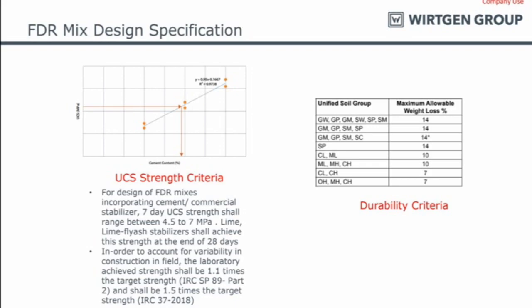As per the specification for FDR mixes incorporating cement as well as commercial stabilizer, your 7-day strength should come in between 4.5 to 7 MPa. Some of the commercial stabilizers claim that we get very high strength, maybe 8 MPa, 10 MPa. It's not recommended because the more the strength, the more brittle the surface will be, and there will be more chances of cracking of the FDR layer.